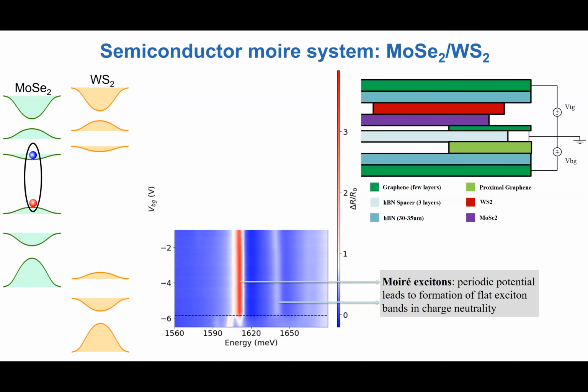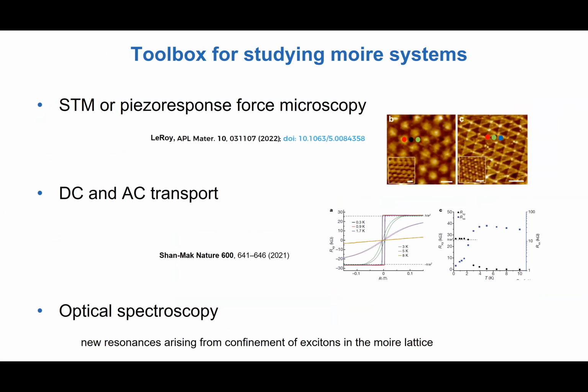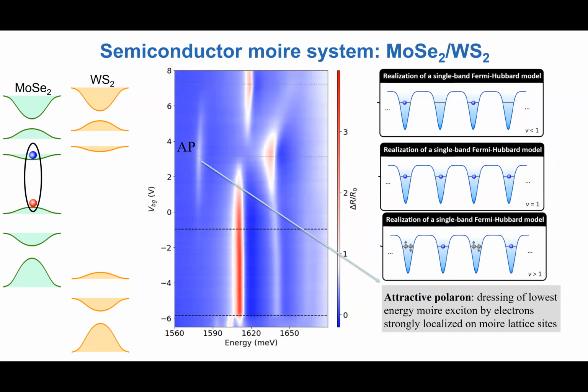Okay, so when I introduce electrons, the spectrum changes dramatically, and I must say upfront that I do not understand many of the features here, but I do understand what happens here. This is the attractive polaron resonance, the one associated with the molecular state. So as I introduce electrons, I put electrons into these moiré sites. When the filling is less than one, I would expect these electrons to hop around using the